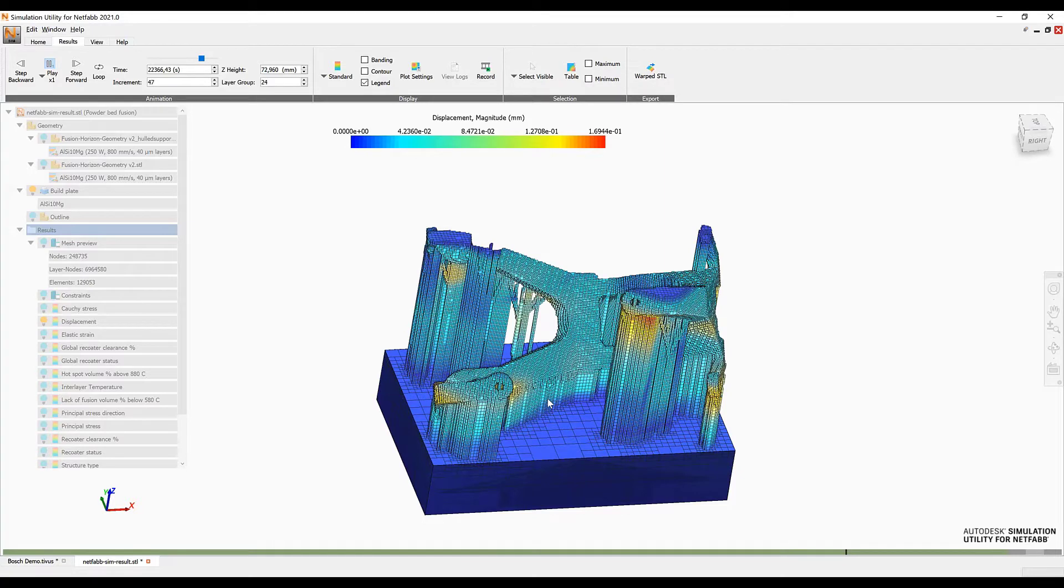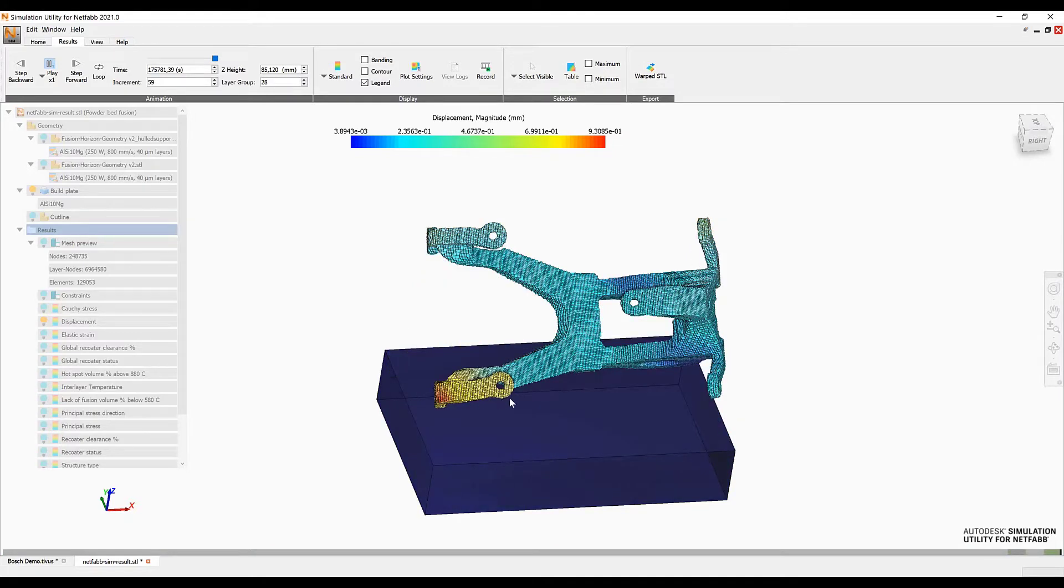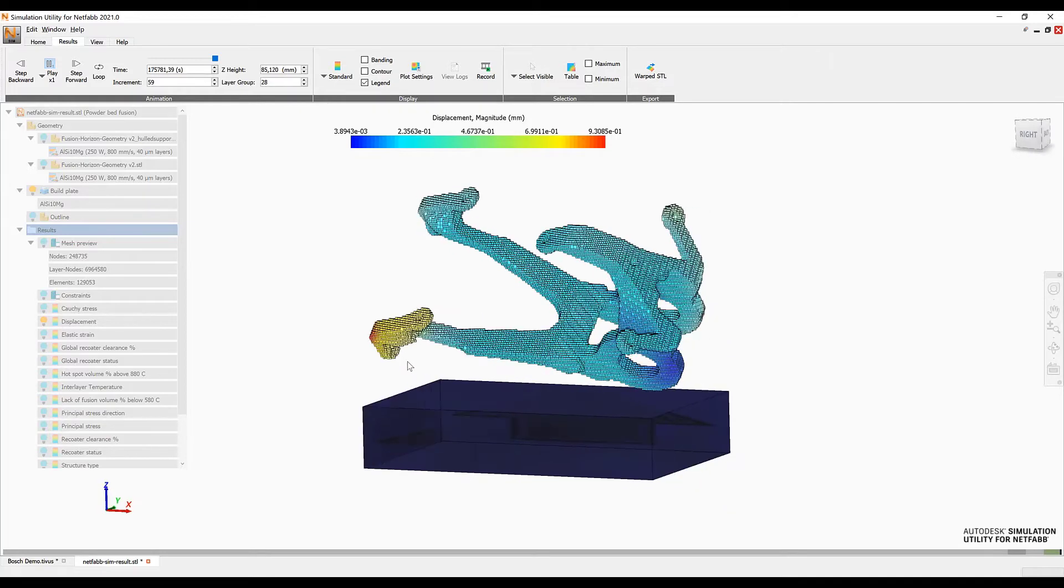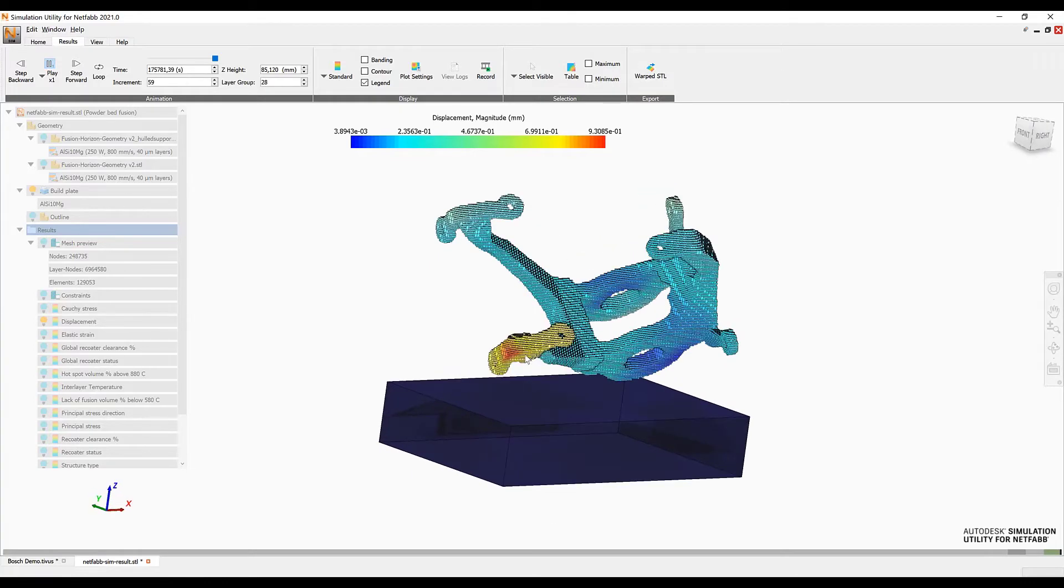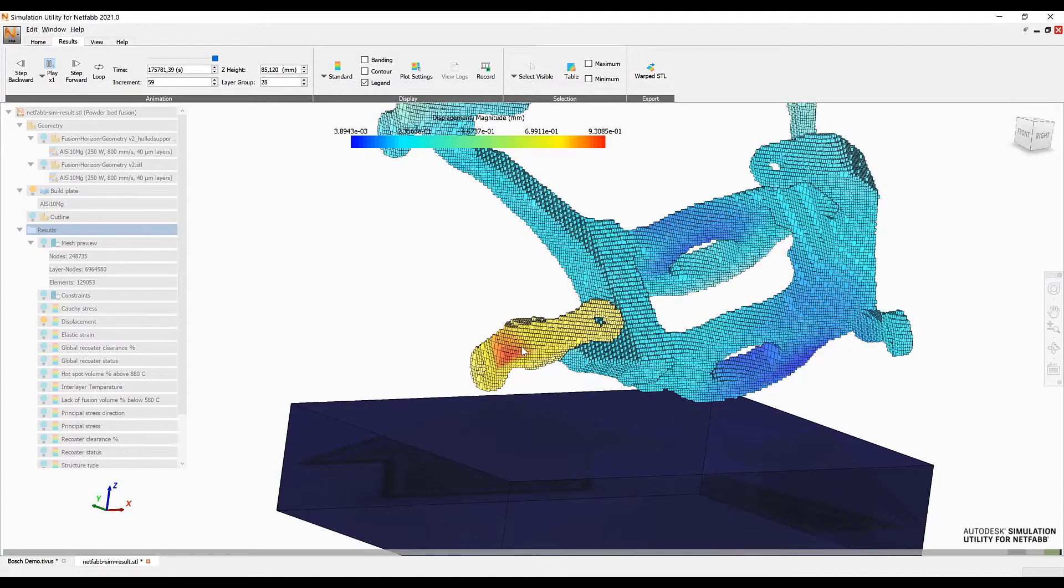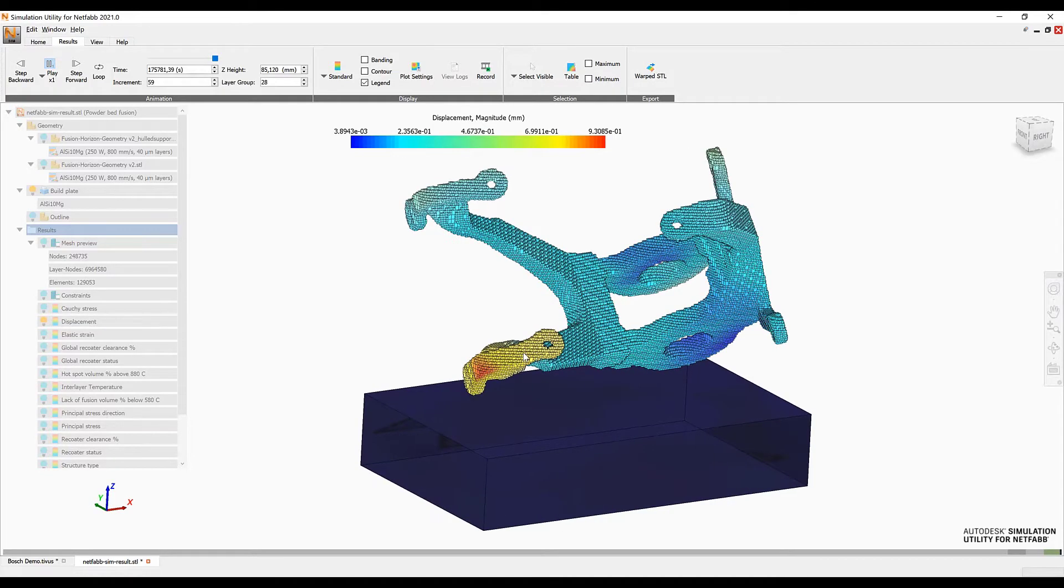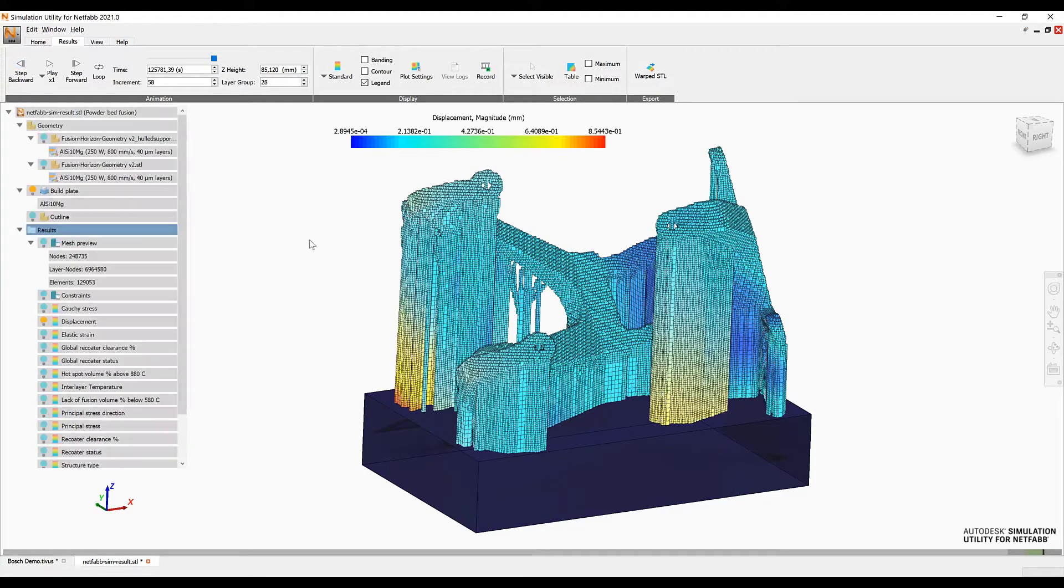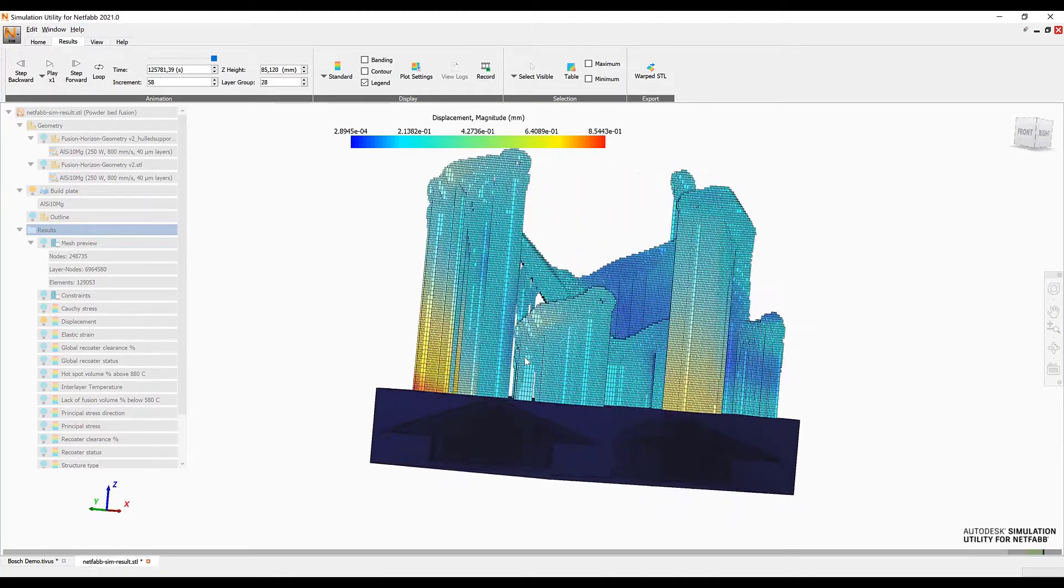As we can see we have different areas of the part in which the support is working rather fine. We do not see any further displacement happening but there are other areas that are mostly affected by the displacement and are possibly going to break away from the build platform or even from the support, such as the area right here in front of us that is colored in red here at the bottom of the part. The area in yellow and red has been displaced around about one millimeter after the removal of the support geometry. If we go one time step back we can see that here the displacement is not that strong yet, however in the back of the part we can see that there is displacement happening right at the bottom area of the support.